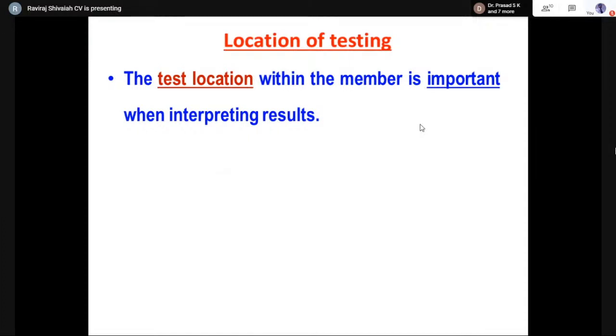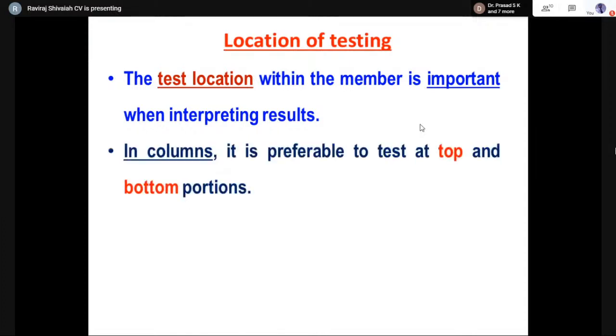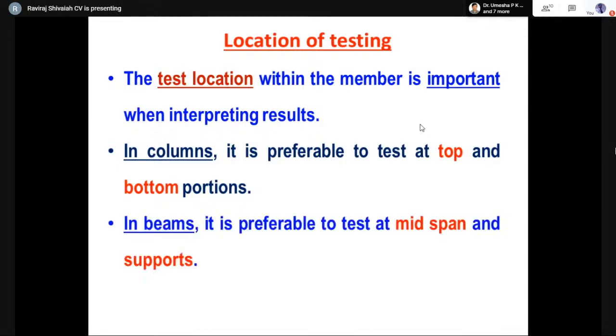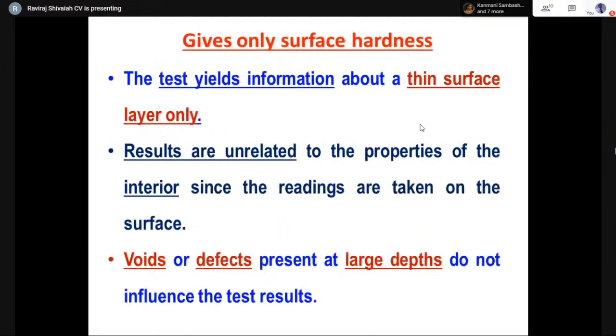Again, test location is also equally important. In columns, we normally perform the test at the top and bottom portions. In beams, you can do it at mid-span and supports, because these are the places where you expect the moments to be quite high, or the forces to be quite large. So always try to zero in on important locations and then do the test.